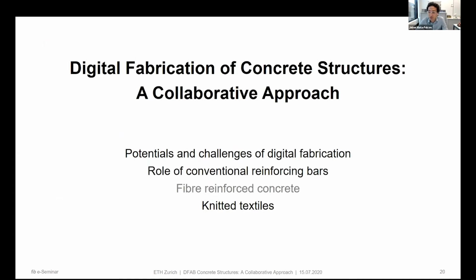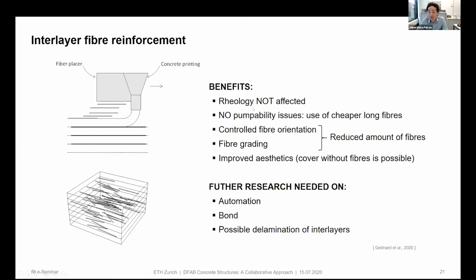Then we have conventional reinforcement, but of course for more complex shapes, fiber reinforced concrete also has a high potential. And we have implemented fiber reinforced concrete in several technologies in the concept that we call interlayer fiber reinforcement. What is this? Instead of placing the fibers in the concrete mix, if we are doing an additive manufacturing concrete process, why not do a separate additive or placing process for the fibers? In this way, we 3D print a layer, and then we place the fibers separately.